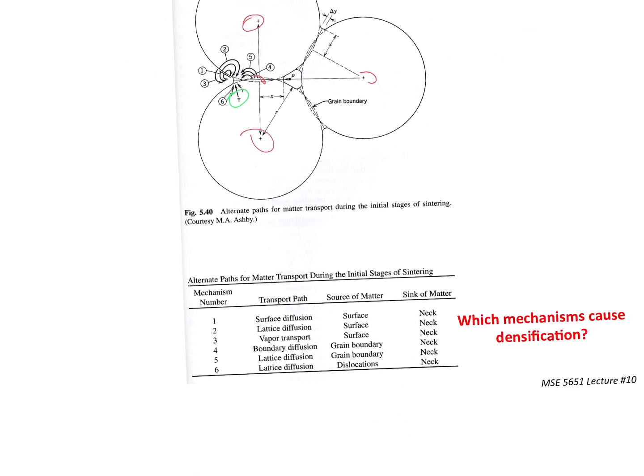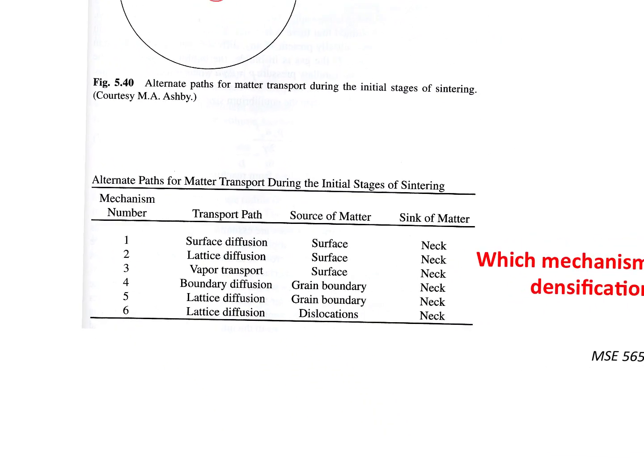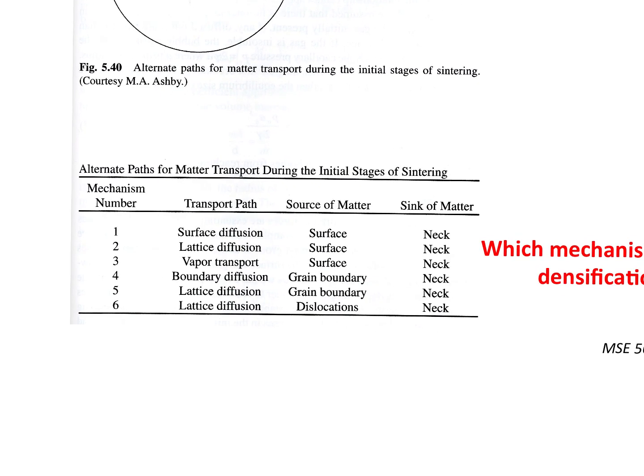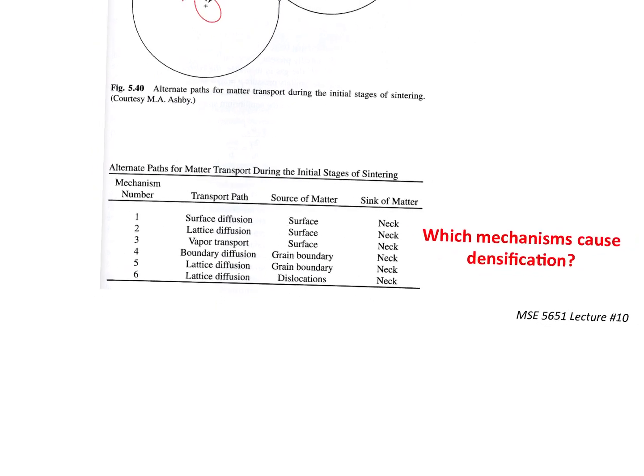And so what we've got is a series of mechanisms, 1 through 6: surface diffusion, lattice diffusion, vapor transport, boundary diffusion, lattice diffusion, the source of the matter and the sink of the matter. And you see the sink for all of them is a neck. You want to put stuff in that neck to take advantage of the fact that it's a concave area. And we have 6 of these, which mechanisms actually allow for densification.